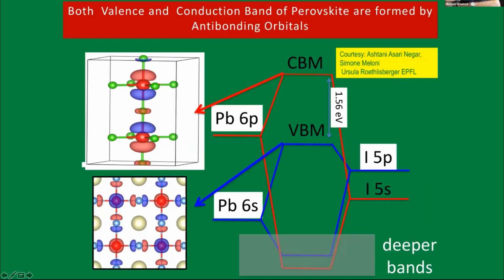And so what is unusual about perovskites is the band structure. They have a valence band and conduction band. They're antibonding in nature. And what that tells you is if you break a bond, it doesn't produce a defect in the band gap, because breaking a bond stabilizes the system. It's a little bit weird to say that, but since these bonds are antibonding, that's a special feature of these materials, and it helps to avoid defects. Even with solution processed films, you have low defect levels.